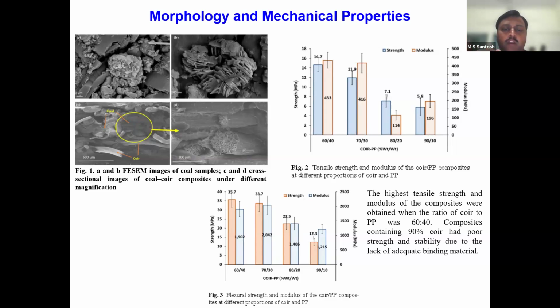Similar properties are also evident in the flexural properties as well. And in this case as well, similar to the tensile strengths, these properties vary significantly. The combinations of 60:40 and 90:10, as you can see, show the highest and the lowest properties in terms of strength and modulus.